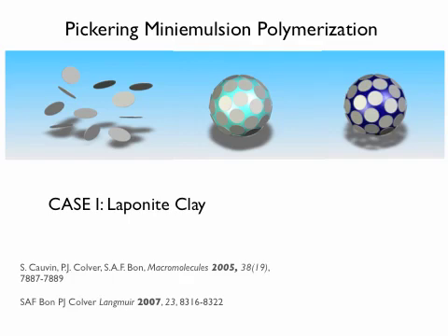So if we have that, we've seen that these particles stick pretty heavily. Once they bump into the droplet, they don't really come off anymore, whereas surfactant molecules quite easily adsorb and desorb. So you might argue that it might be rather difficult to see this happening. If you would just shake, maybe the adhesion energy of the particle is too large, and therefore you can't really match droplet size with respect to number of particles.